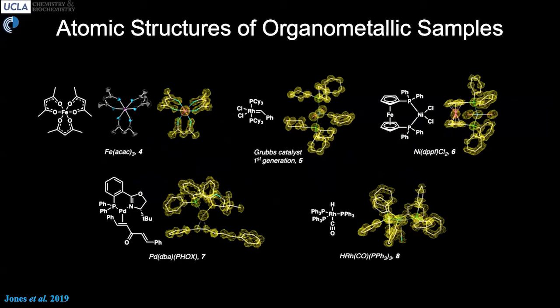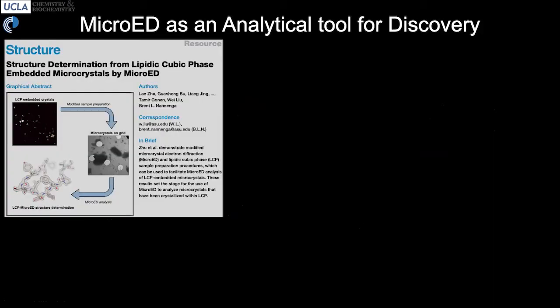This was one of the early works that we collaborated on together, trying to determine structures of organometallic small molecules. Crystals of those were diffracted on electron microscopes here on campus, we were able to determine a number of structures, and showed that even at room temperature, we could obtain high quality diffraction from some of these molecules. And that was quite impressive.